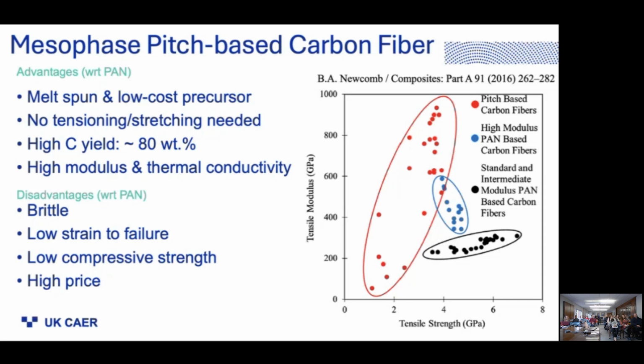I don't think that's the same as saying they're high cost. There's, I think, a pretty large margin in the pitch-based carbon fibers. But these disadvantages, particularly the low strain to failure and the brittleness, is really the issue. And the PAN-based fibers offer a higher, tougher fiber that's more stretchy, and toughness wins at the end of the day for a lot of these composites. After all, you don't want to build primary aircraft structure that's brittle. You want it to be light and strong and not to deform a lot, but you don't want it to crack like an egg.